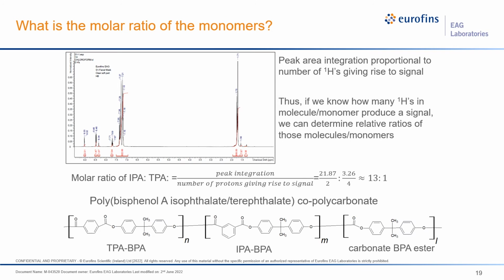NMR is a quantitative technique. So for this, we can use the peak area integrations, which give rise to these signals. And if we know how many protons in a specific monomer create the signal, we can determine the relative ratio of these in the polymer. So if we're looking at what is the ratio of the isophthalate to the terephthalate, we can divide the peak integrations by the number of protons giving rise to that signal to determine there's about 13 times more of the isophthalate relative to the terephthalate.